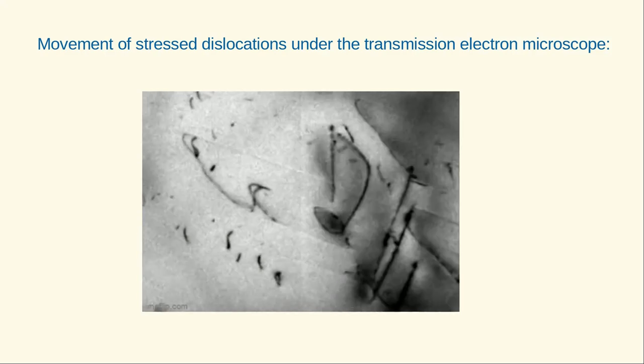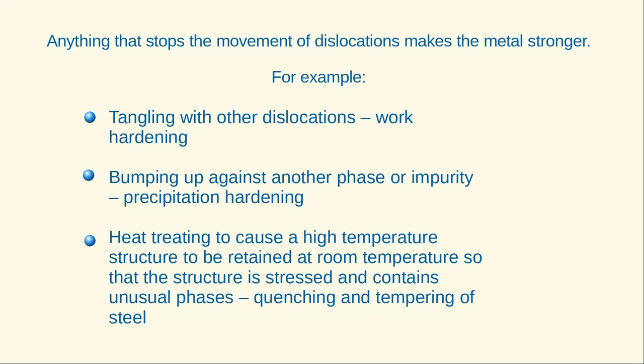So I've said that metals deform by movement of dislocations. Anything that stops the movement of dislocations makes the metal stronger. For example, if dislocations tangle with other dislocations, that means they can't move, and that's called work hardening, which you may well have heard of, I don't know. The other thing that stops dislocation movement is bumping up against another phase or impurity. So if we've got precipitates or bits of another compound in the metal, that's called precipitation hardening. Heat treating can cause a high temperature structure to be retained at room temperature, so the structure is stressed at room temperature and contains unusual phases. And that's how the quenching and tempering of steel happens. It stops dislocations moving or makes it harder.